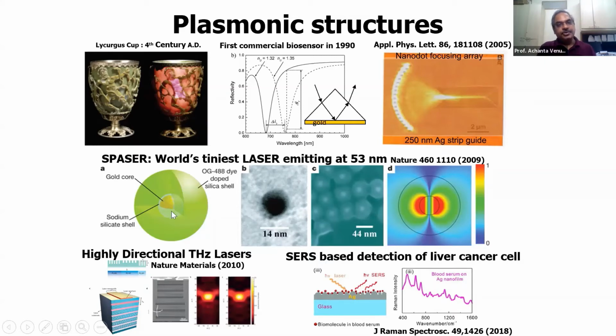So you have a gold core surrounded by a sodium silicate shell, which is filled with this dye. Right. So when you shine light on this, you excite the dye. So the dye emits, which will excite the localized plasmons at the core. Once the localized plasmons are excited, you have a very strong local field, which leads to more absorption in the dye, and the dye will emit more. So you have this amplification which happens. So this is the world's tiniest laser.